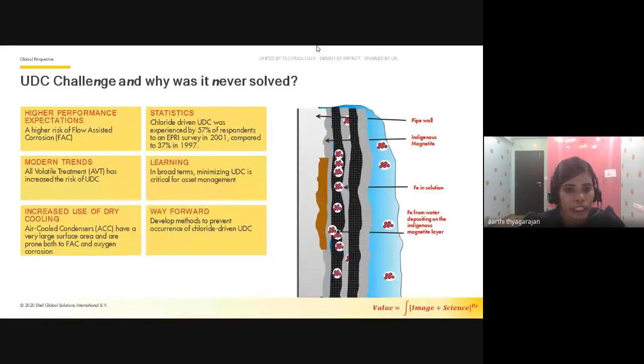In this project, what we are primarily concerned with was the chloride driven mechanism. This is because of several factors that have conspired over the last 20 or 30 years to make this an increasingly prevalent failure mode. Those factors are the drive for high performance, for example, we want to increase flow velocities and increase production in the feed water piping, hence leading to higher heat fluxes. The second reason is the move away from phosphate based treatment towards all volatile treatments, where we are using very harsh chemicals. And the third is the increasing use of air cooled condensers.